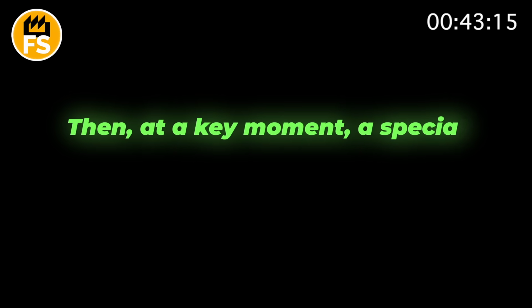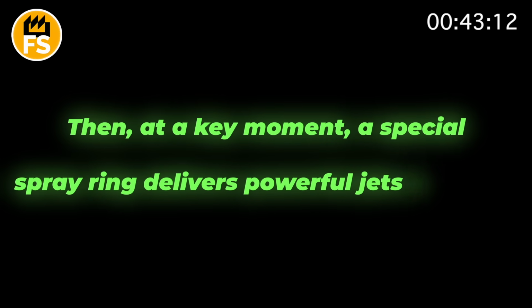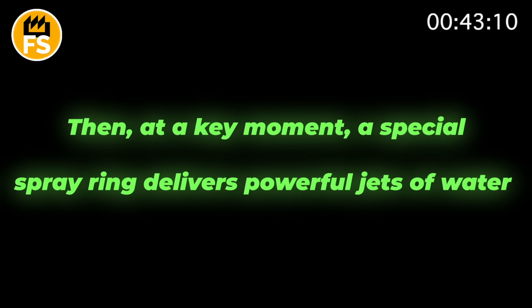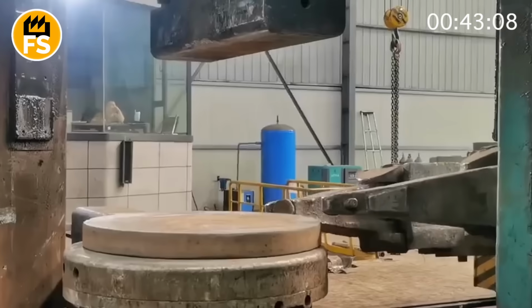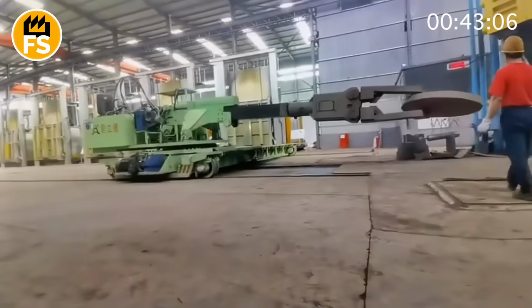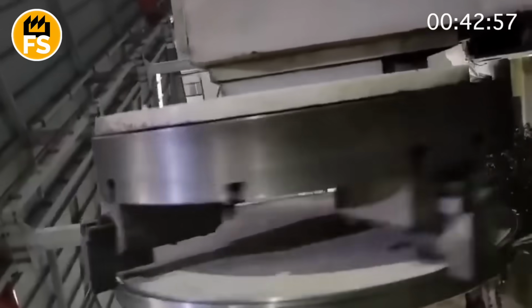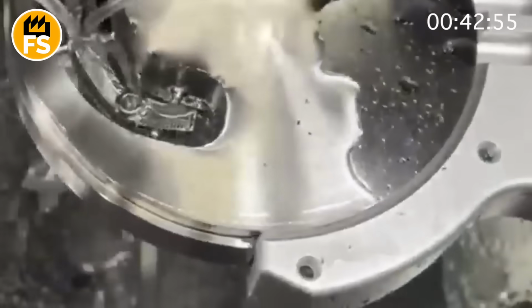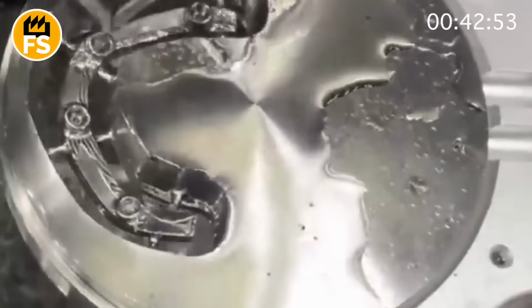For this, the entire wheel is uniformly heated to a temperature of about 1,550 degrees Fahrenheit. Then, at a key moment, a special spray ring delivers powerful jets of water exclusively to the rim and flange of the wheel. This instantaneous cooling, or quenching, drastically changes the crystal structure of the steel on the running surface, making it extremely hard. At the same time, the plate and hub cool slowly, in the air, which allows them to retain a more ductile and plastic structure.